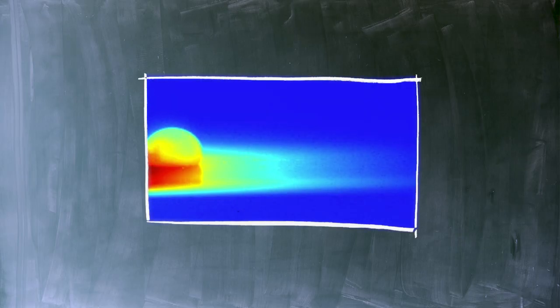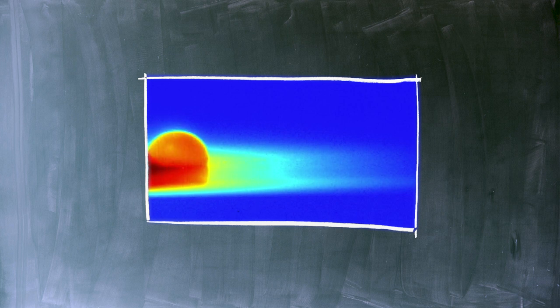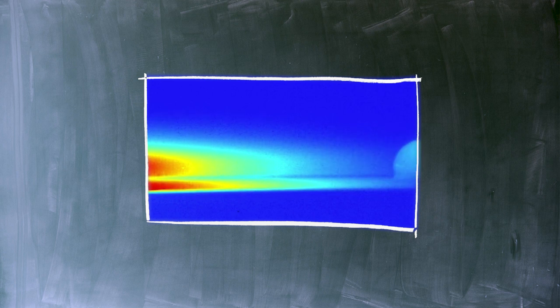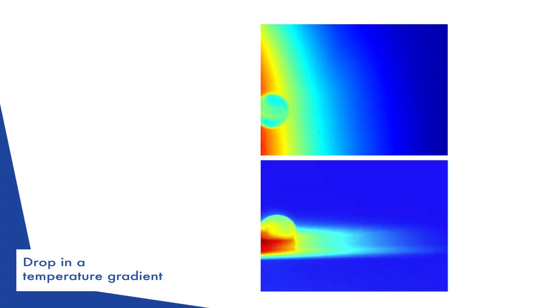A drop on a substrate with a non-uniform temperature is likely to move under Marangoni forces. In order to make this effect spectacular, we can use a textured solid impregnated with oil which minimizes pinning, whose action opposes such motion. In this infrared movie, you can see both side and top views showing the behavior of a water drop deposited on a solid impregnated with silicon oil. Placed on the hot part of the solid, whose temperature is 70 degrees Celsius, the drop first heats up until it matches the temperature of the substrate and then moves to the cold, 50 degrees colder, at a velocity of typically 1 mm per second. This drop is drawn by the contrast of the oil surface tension between its two edges. Surface tension being larger on the cold side, the capillary force attracts the drop towards this region.